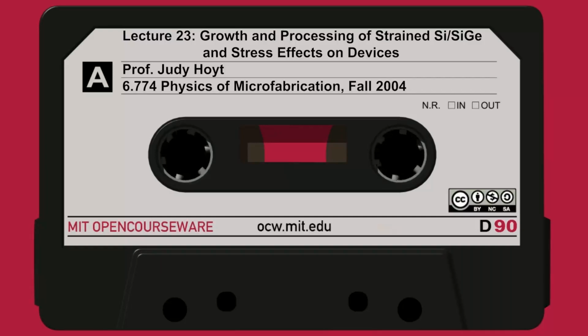Slide 17 shows some metrology. The question you may be thinking is, well, how do you really know? All right, your mobility went up, but how do you really know that the layers are strained? Especially when they're so thin, how do you measure strain in a layer that's only 100 angstroms thick? You really can't use X-ray diffraction. X-ray diffraction on a 100 angstrom layer is going to be really tough because the layer is very thin. So how do you measure that change in the lattice parameter?